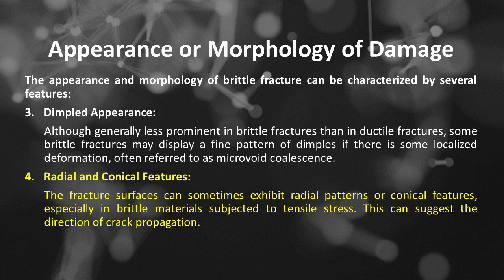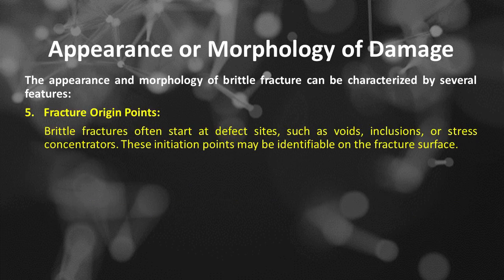Number 4 is radial and conical features. The fracture surfaces can sometimes exhibit radial patterns or conical features, especially in brittle materials subjected to tensile stress. This can suggest the direction of crack propagation. Number 5 is fracture origin points. Brittle fractures often start at defect sites, such as voids, inclusions, or stress concentrators. These initiation points may be identifiable on the fracture surface.